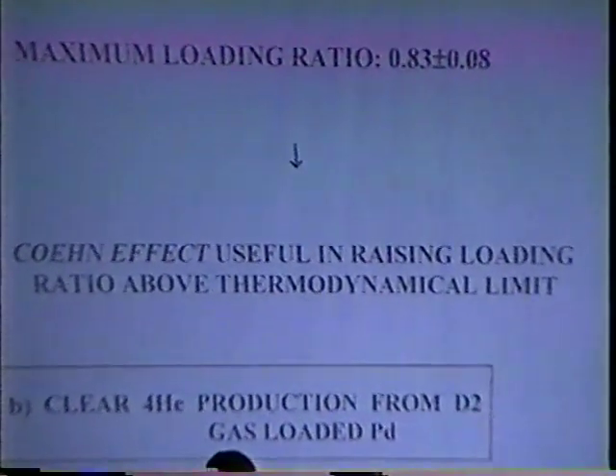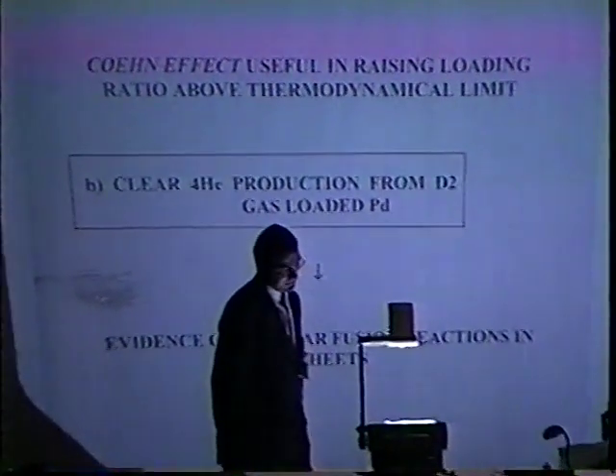So the conclusion that we can at the moment reach is twofold. From one side, a high value of loading ratio around 0.8. It's of course a mean value, as we have no information about the local concentration of deuterium till now. And second, it seems clear that we are in fact increasing the loading ratio above the thermodynamic limit. But the most important is the production of helium-4 from the D2 gas-loaded system that could create variants of nuclear fusion reactions in Pd sheets.